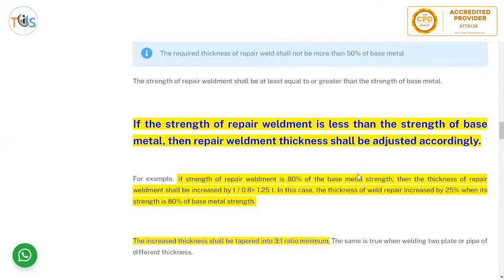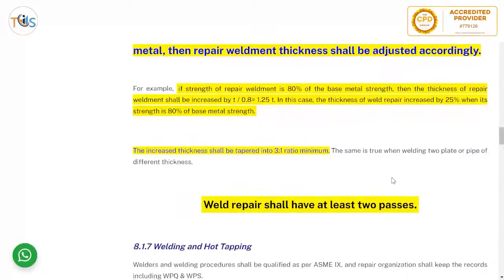Now, how is it adjusted? For example, if the strength of the repair weld is 80% of the base metal, then the thickness of the repair weld should be increased by T divided by 0.8. So the thickness of the weld should be 1.25 T. So the weld repair is increased by 25% when the strength is 80% of base metal. In this case, the increased thickness shall be tapered at a 3:1 ratio minimum. This is the same way as when you join two plates with unequal thickness, different thicknesses, and you use a taper of 3:1.